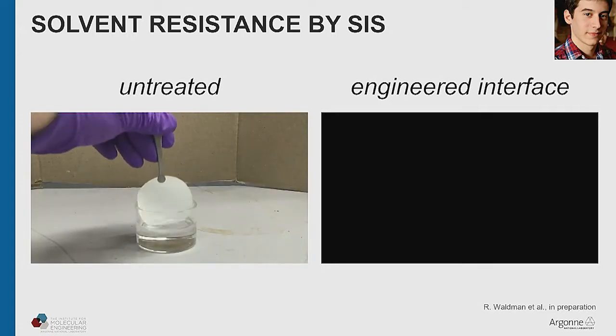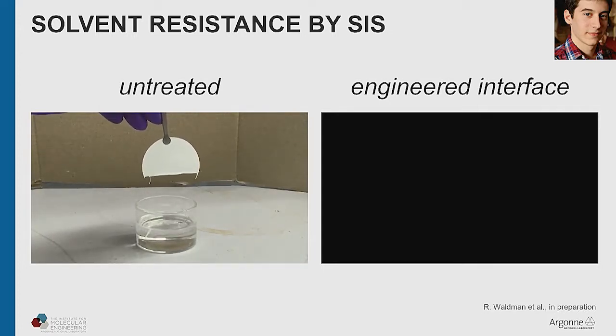Now, this isn't quite fouling, but it's another example of making a more resilient membrane with this kind of interface engineering strategy. Here we do this with SIS instead of ALD. And the resistance we're imparting here is to solvents. So membranes are also often used in environments where there are solvents present, sometimes in water. And if you take a commercial polymer membrane like this one here and dunk it into an aggressive solvent that I think is chloroform, you saw what happened. That's a pretty bad result for a membrane. It was basically instantly gone.